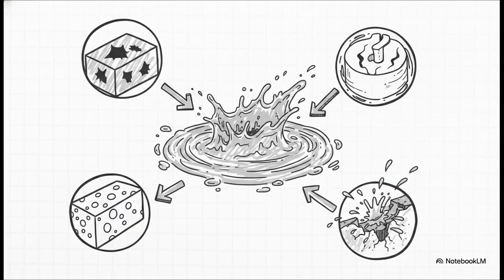Turbulence is absolutely the enemy of a smooth, high-quality cast. Instead of flowing in this nice, streamlined, laminar way, the liquid metal gets super agitated and erratic. So why is that bad? Well, three main reasons. First, it accelerates the formation of metal oxides, which get trapped inside and weaken the final part. Second, it promotes the absorption of unwanted gases, leaving you with microscopic bubbles or voids. And third, it severely aggravates mold erosion. The violent impact of the liquid metal literally wears away the interior surfaces of your mold.